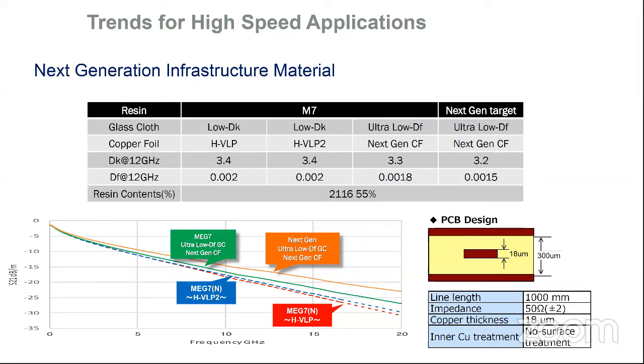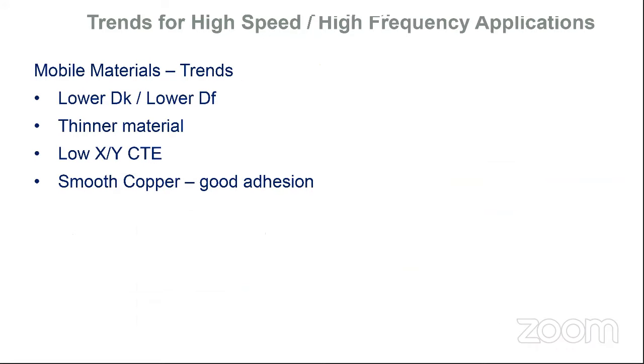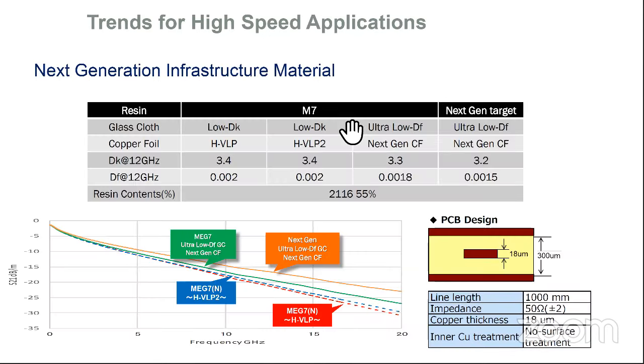This is a slide I just had to throw in there because given the direction that we're going, using an ultra low loss product, and as this example will illustrate where we are and where we're going, at 12 gigahertz, looking at copper foils and glass, you can see where our data would indicate we are centered. You have to take into consideration the resin content. In this case, it was a 2116 55%. But as we move forward with the same settings, we anticipate that we will be looking at DF in that 0.0015 and DK at 3.2.